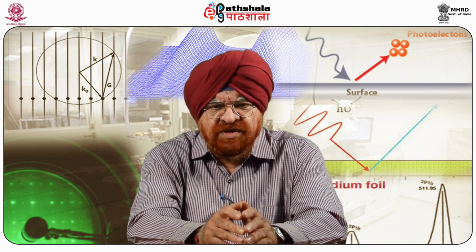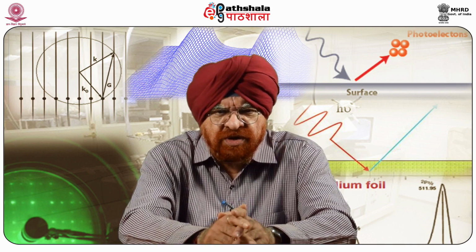For the structural analysis of atomic positions in surface unit cells, LEED I-V analysis has been developed with an accuracy of less than a few hundredths of an angstrom. Furthermore, for determination of complex surface structures, this has been automated. Besides the intensity of diffraction spots, the profile and position also contain important information about the surface morphology, which can be analyzed by spot profile analysis LEED, or SPA-LEED.